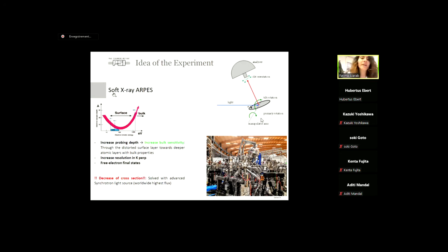Now, why is soft X-ray important here? Because soft X-ray, in terms of photon energies, of course, is higher than the UV rays. All right. So by increasing the photon energy, we are increasing the bulk sensitivity in the material. All right. And this is because we are increasing, of course, the probing depth. So here we can not only reach the surface, but also the bulk. And if we have an interface, we can go through the overlayers to reach the interface where we hope to measure. Okay.